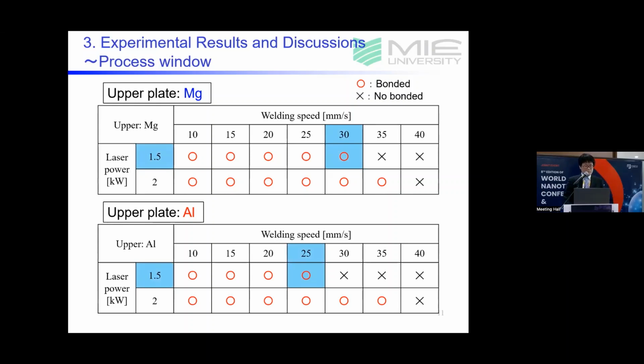At a laser power of 1.5 kilowatt, bonding was achieved up to a welding speed of 30 millimeters per second when the upper plate was magnesium, and up to a welding speed of 25 millimeters per second when the upper plate was aluminum. Also, as the laser power increases, the maximum welding speed also increases.